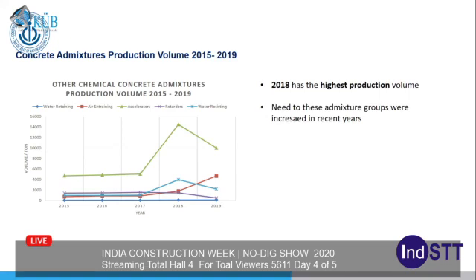And we can see no increase and no decrease between 2015 and 2017, but after 2017, these 5 groups started to increase, and 2018 has the highest production volume for all. And after that, 4 of them started to decrease. Only air entraining concrete admixtures increased in 2019. Totally, we can say that these admixture groups increased in recent years.